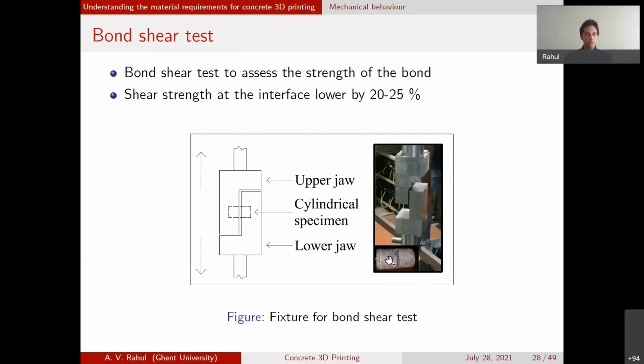Then if you do that on a specimen without the presence of an interlayer, so suppose you drill the same size core from a mold cast concrete without any interlayer, when you compare the shear strength values for both, you see around 20 to 25% decrease. So this level of decrease can characterize the interface properties of the printed concrete.